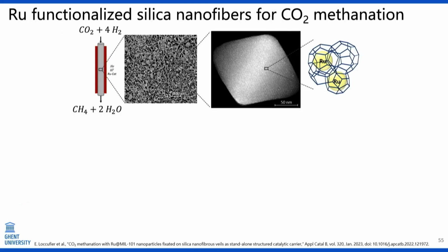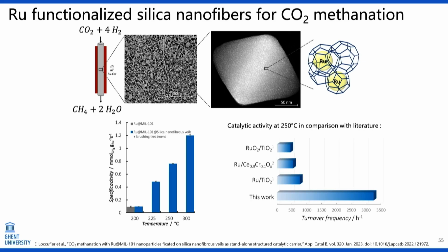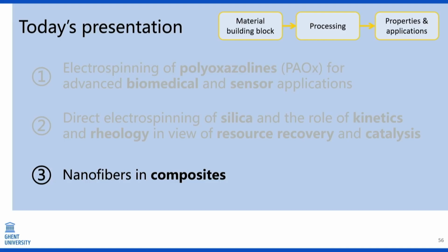Another example there is loading them with ruthenium functionalized MOF particles to do CO2 methanation, and then, for instance, by just loading them on the silica membranes, we have a much higher turnover frequency compared to the MOF particles alone on other carriers. So also these silica membranes, completely different building block with completely different end applications, but both as interesting. And then as a third research line, I would like to introduce you our work on using nanofibers in composite materials.